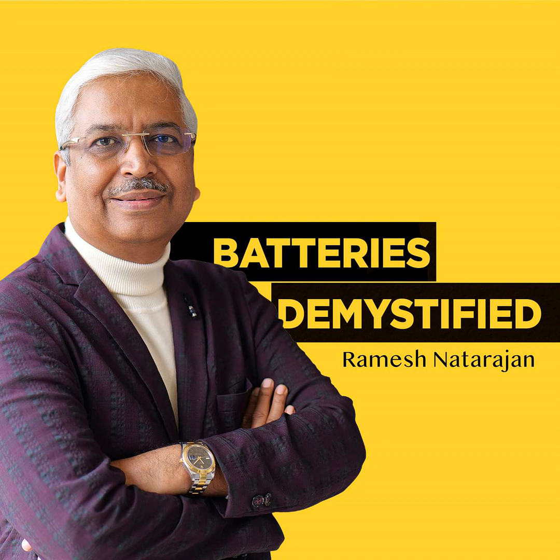Sure. So it really depends on the application and on the region. In Europe, we know that they generally use around 0.25 weight percent on lead oxide, whereas in the United States, it's typically closer to 0.3%. And in China, we hear that customers are using as much as 0.4%. So it really depends. The other thing is that there's a trade-off in battery performance characteristics.